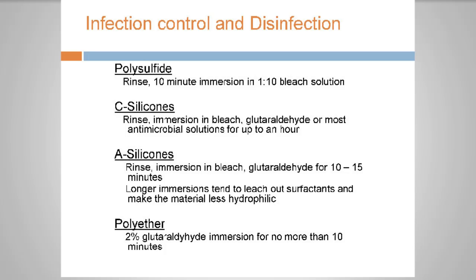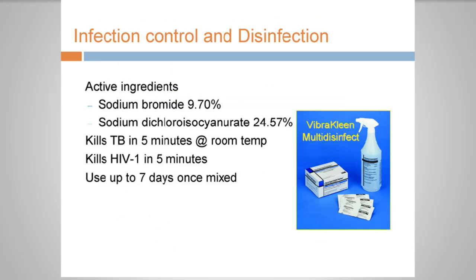Polyethers, on the other hand, use 2% glutaraldehyde, no more than 10 minutes. If you're doing it longer than that, again, they're kind of hydrophilic. They will absorb moisture, and they could have dimensional stability issues, causing tight-fitting crowns or ill-fitting crowns. So be careful with that.